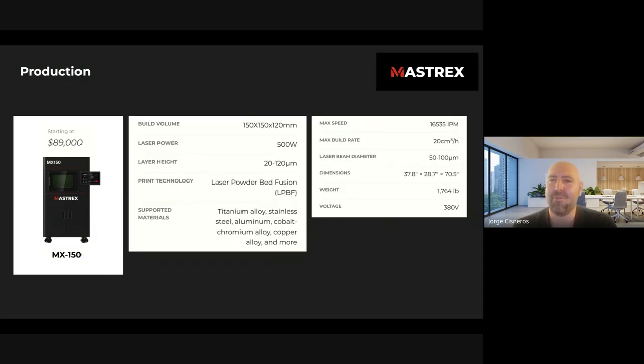That can be really useful for removing powder after you're finished printing, or even removing all the powder from the machine if you're doing a material changeover. And as we had stated, one of the benefits of this technology is that you can reuse the majority of the material, so you don't have a lot of waste. With the powder collection system, you can collect all that material that wasn't used.